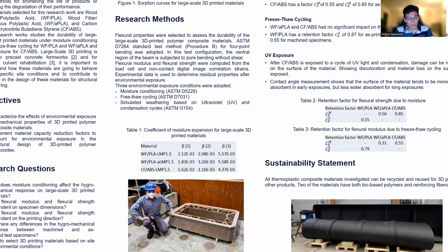Experimental data is used to determine residual properties after environmental exposure. Three environmental exposure conditions were adopted. The first one is moisture conditioning following ASTM D5229, then freeze-thaw cycling following ASTM D7031, and simulated weathering based on ultraviolet and condensation cycles following ASTM G154.